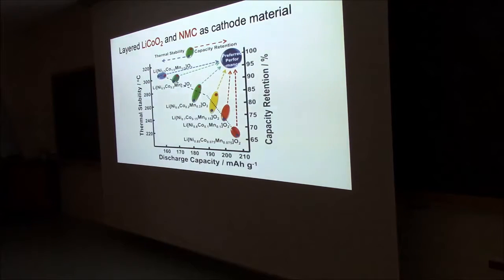And I must say that the way that normal batteries are being made, I normally tell my students like this. Just mixing stuff. There's not really control on what can happen. They make powders, and they look into the grain sizes, what is the effect of making something smaller, you have a lot of surface area against the volume. And then they put coatings around it. And that's where the oxides come in as well. So the normal coatings are just to passivate it, aluminum oxide or anatase, titanium oxide, but also lithium tantalate, lithium niobate, and a lot of these oxides. But this is a problem, and this is where I would say a big part of the battery community is looking into.